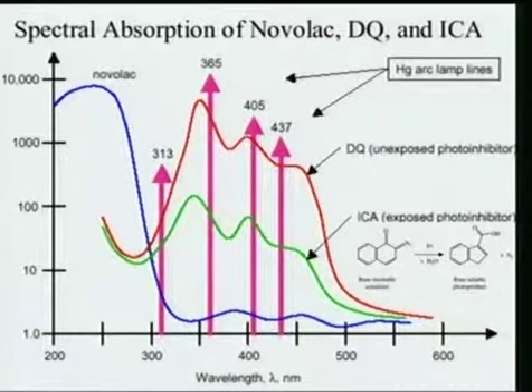But what happened was the resin that we used, called Bakelite or Novolac resin, this will help you for a little context. Airline plane brakes use Novolac resin as the material for the braking. So there's a little reality for your life. Anyway, this thing has a high absorbance. Why is that a problem? Well, I need the light to get through the film to convert this material so that I can develop it. And because we were using this Novolac resin, notice it absorbs very low down here, not much absorbance. But as soon as we got down into this deep UV area, wham! You're getting zero light at the bottom of the film.